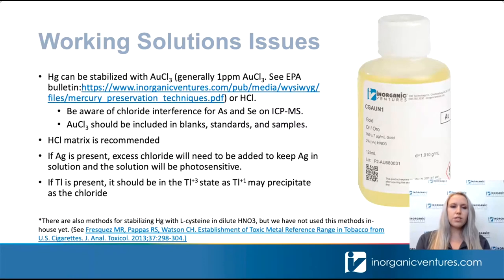An alternative solution is to stabilize your mercury by adding 1 ppm gold trichloride. This is going to add a chloride interference if you're using ICP mass spec on arsenic and selenium. However, this interference can be overcome if you add gold trichloride to your blanks, standards, and samples at that 1 ppm concentration. The chloride level is not going to be high enough to cause significant issues as long as they're accounted for in your blanks and standards along with the samples.